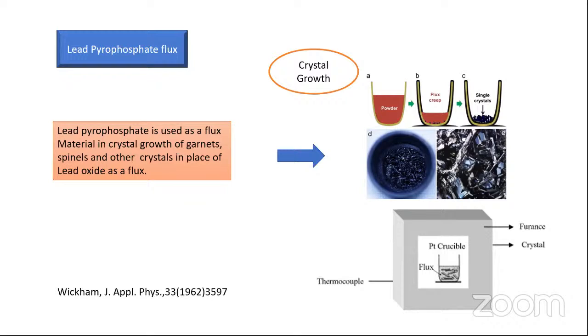So lead pyrophosphate is used as a flux material in crystal growth of garnets, spinels, and other crystals. So this is again a very popular flux material, and a schematic diagram is shown over here. The powder, the flux, and the grown crystals. So these are the grown crystals, and this is the rough arrangement of the setup where the platinum crucible in which the flux is there is heated in a furnace, and after heating at a suitable temperature, the flux is removed and crystals are obtained. So this was reported very long back in 1962. I have covered the references right from 1953 to 2020. So different types of research have been reported on metal pyrophosphate materials.